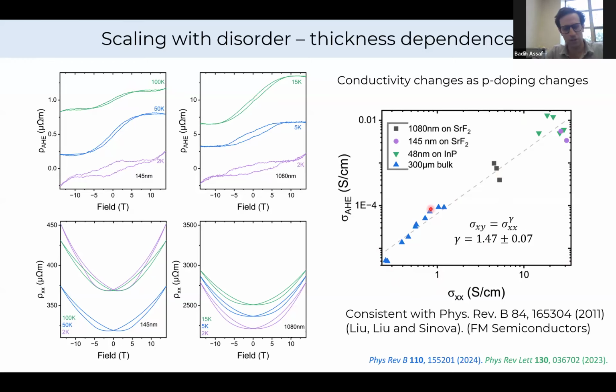So we're calling this anomalous Hall effect the pristine anomalous Hall effect of MnTe because it occurs in a phase of the crystal that's unaffected by strain, that has essentially the same lattice parameters as bulk. And what I'm going to show you next is that this is not quite the case for some of the films that have been studied so far, including ours, and that are grown on III-V substrates.